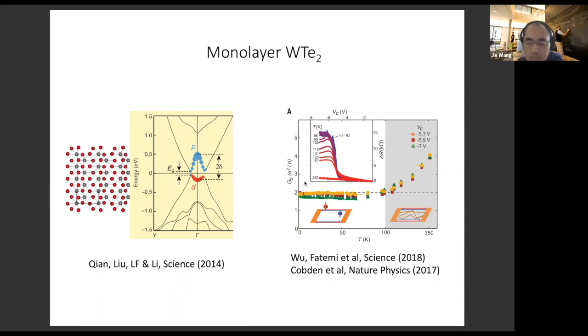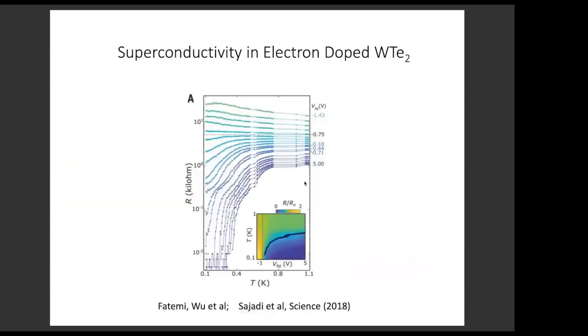Now, what's really remarkable is that in 2018, two different groups, from MIT and from the University of Washington, Seattle, both found superconductivity in electron-doped tungsten ditelluride. These are basically resistance as a function of temperature for different dopings controlled by the electrostatic gate voltage. And at least it looks like a direct transition from insulating behavior to superconducting behavior. So there's no evidence of an intervening metallic state. It really looks like doping turns an insulator into a superconductor.